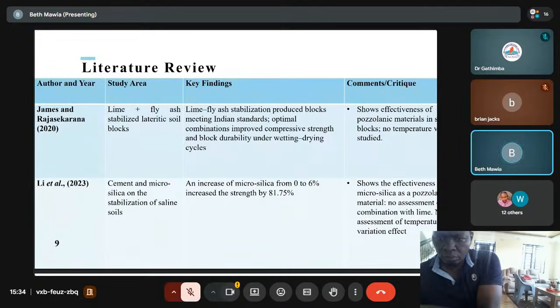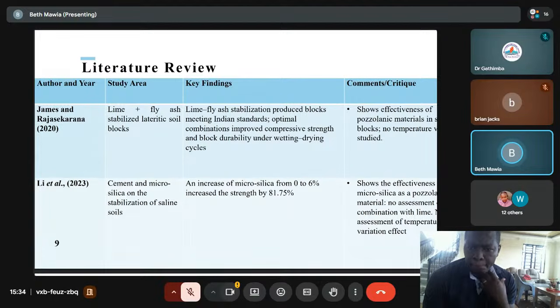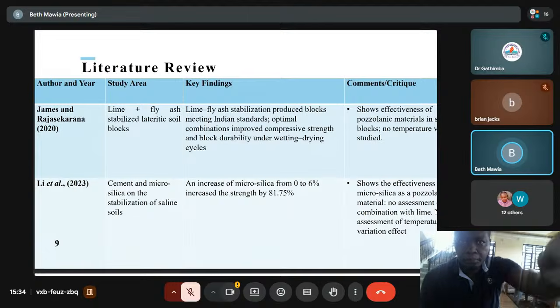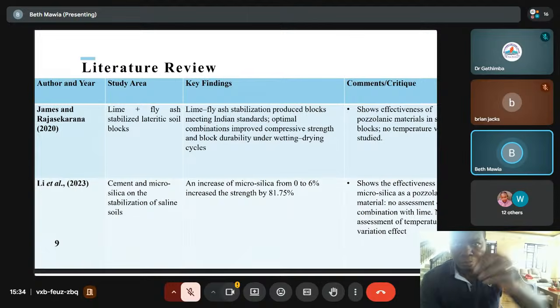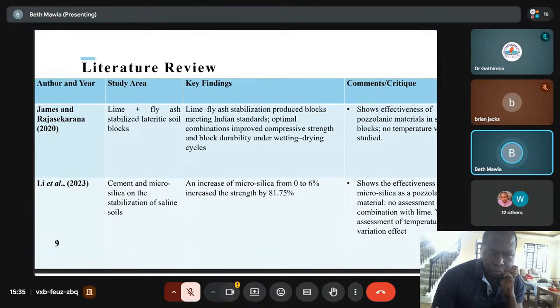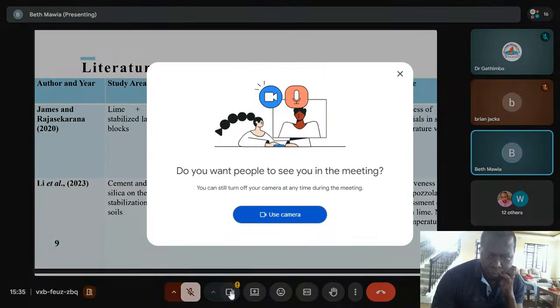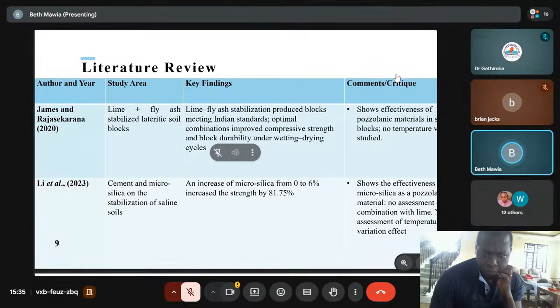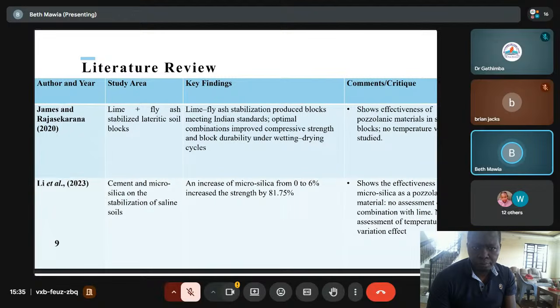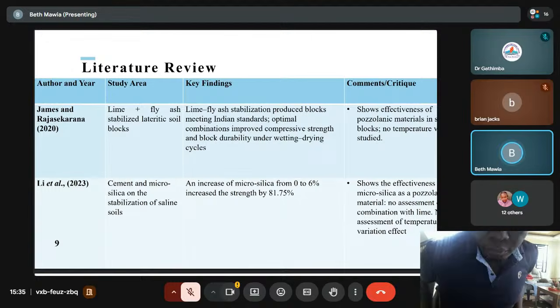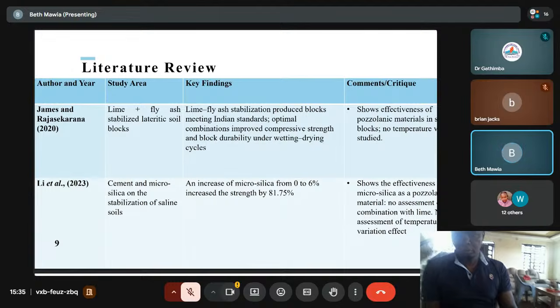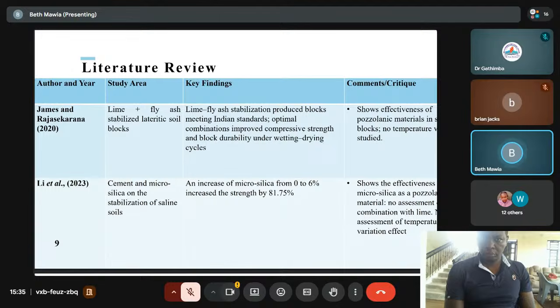Literature review, we reviewed some scholarly works. For example, there's this study by James and Rajasekaran on lime and fly ash. They found that lime and fly ash can be used to stabilize blocks, and they met the Indian standards. But in our critique, although they show how effective the pozzolanic materials are, they did not study anything to do with temperature variation. We also have another study by Li et al. This one they did cement and microsilica, and although they showed the effectiveness of microsilica in that it increased strength by 81.75%, they did not assess temperature variation, and also there was no assessment of combination with lime.